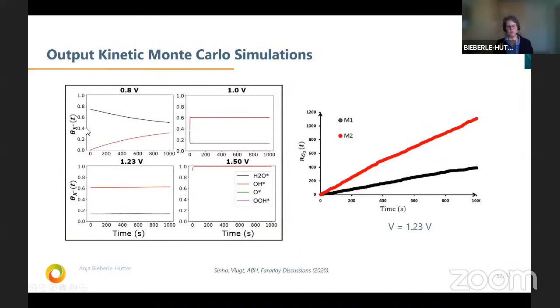the surface species and the dependence on the running time. We did this with two different models. So what we can get out from this analysis is what surface species we have and how they change over time. And this is actually comparable data that we can also get out from the microkinetic model. There we can also get plots of the surface coverages. And actually the next step here is also to compare these two pathways.